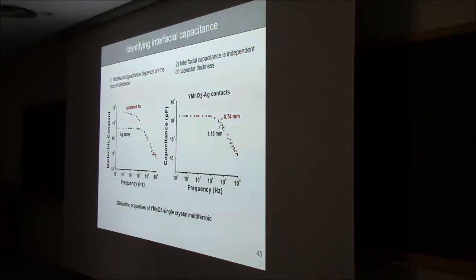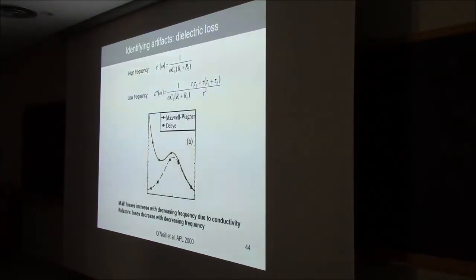Right? Ways in which you can distinguish. You can, for example, change your electrode. If your capacitance depends on your electrode, it means that it's an interfacial effect and not a bulk effect. Or you can change the thickness. Okay? If you change the thickness of your capacitor and the dielectric constant doesn't change, it means that the dielectric constant is not coming from a bulk effect, it's coming from a barrier, the thickness of which you are not changing. Okay?